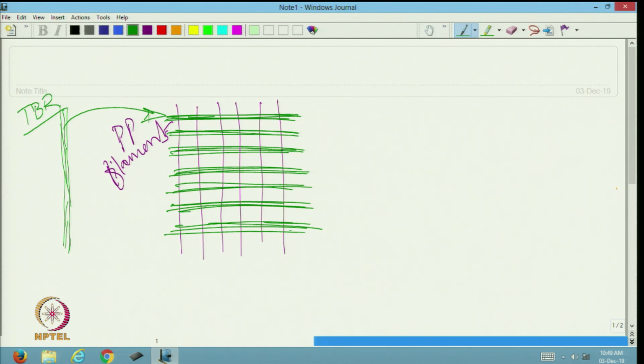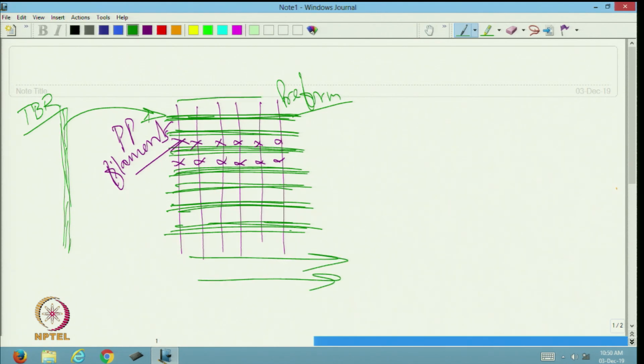Effectively, this is a fabric, this is say preform, and the warp is PP. Once we produce a composite out of this fabric by film stacking technique, this polypropylene will be mixed with the matrix component. Effectively we will see, in this weft direction, this TBR will have the reinforcing fiber aligned only in this direction. So, that is why we call it a unidirectional composite.